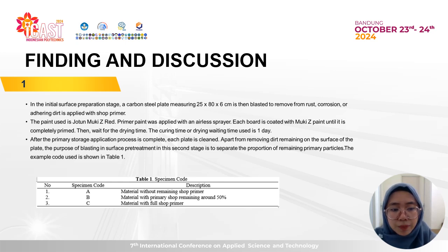After the primer application process is complete, the plate is cleaned. Apart from removing dirt remaining on the surface of the plate, the purpose of blasting in surface pretreatment in this second stage is to separate the proportion of remaining primer particles. The specimen codes used are shown in table 1. Table 1 shows the specimen codes for different types: specimen code A for material without remaining shop primer or 0%, specimen code B for material with primer remaining around 50%, and specimen code C for material with full shop primer or 100%.